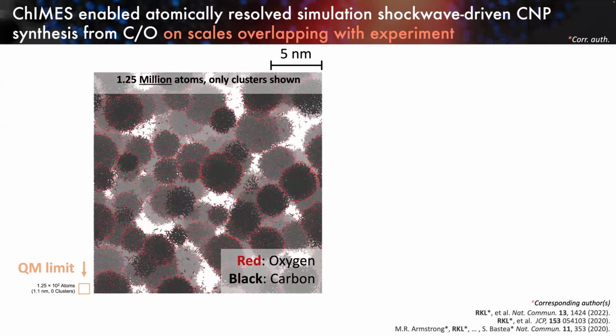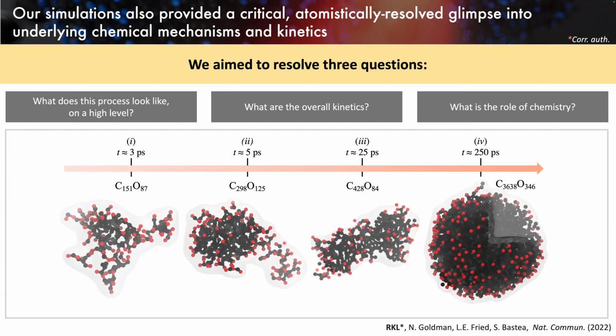From our simulations, we can do things like extract pictures. So this is a cluster growth timeline where we can see at early time we have these low density extended seed clusters that have oxygen in red and carbon in black distributed roughly homogeneously throughout. And as time goes on, we can see our clusters densify, they agglomerate together, and form these nice spherical carbon nanoparticles that have oxygen-decorated exteriors.